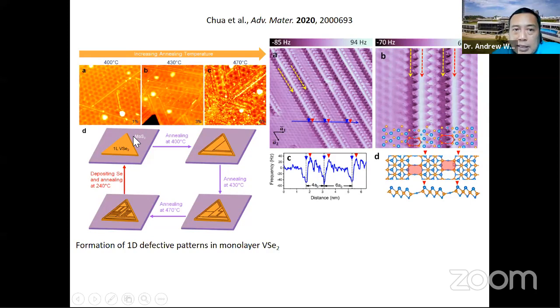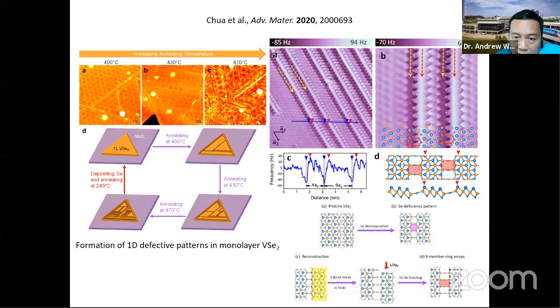After depositing, you see some of these triangular defects, but they're not so many. But if you anneal it, the density of these triangular defects increases, as illustrated here. And if we zoom in on these line defects, we can build a structure of these selenium deficient defects. It turns out that these line defects have a structure as shown here, which requires a displacement of half a lattice constant of the adjacent row. So it forms 8 member rings, as seen in these STM images.